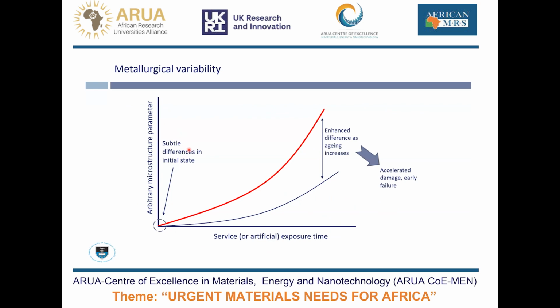So if we then consider this metallurgical variability, instead of having this black line at the bottom, which is predicted behavior, we'll start with a condition which is only subtly different in the initial state. In fact, the difference might be so subtle that we don't actually pick it up in a quality control assessment when we measure the time-independent properties.